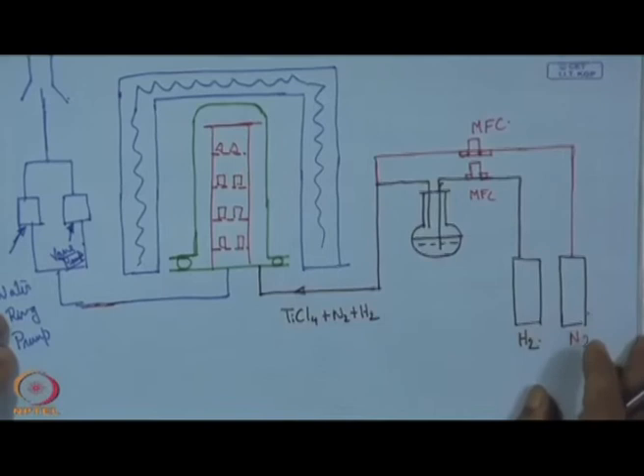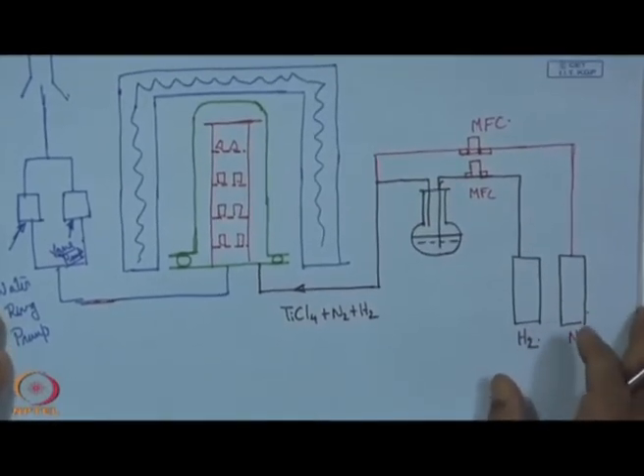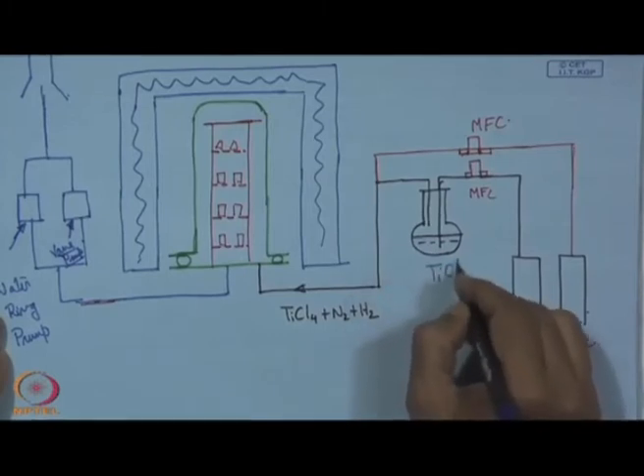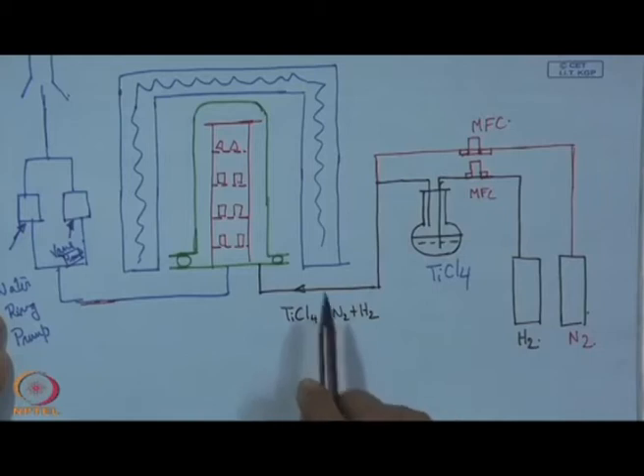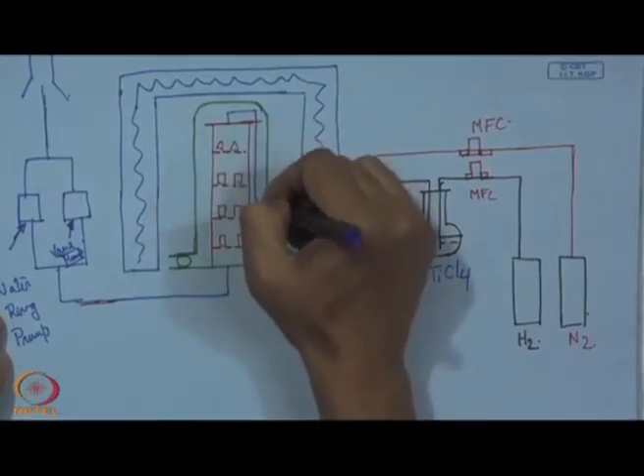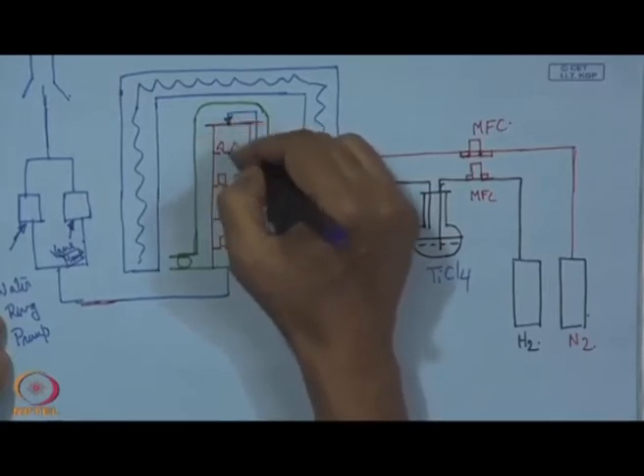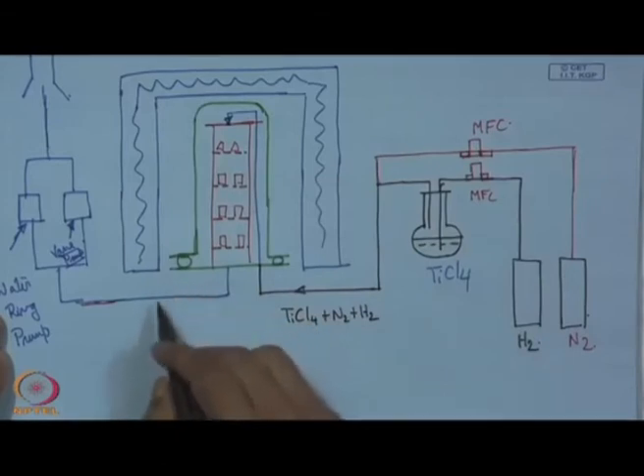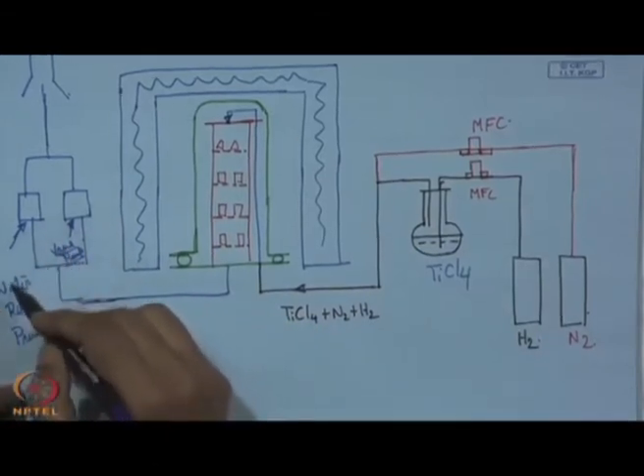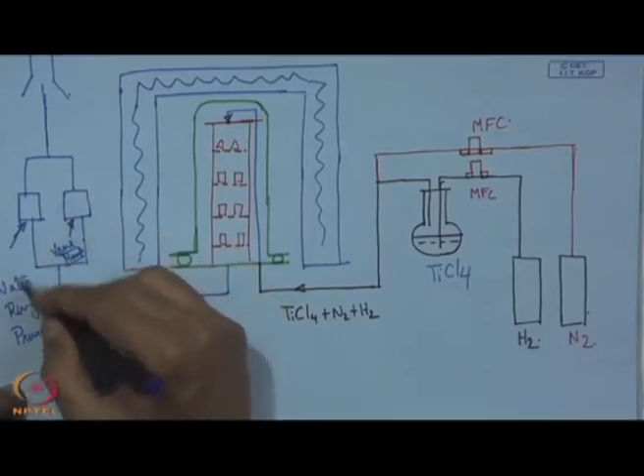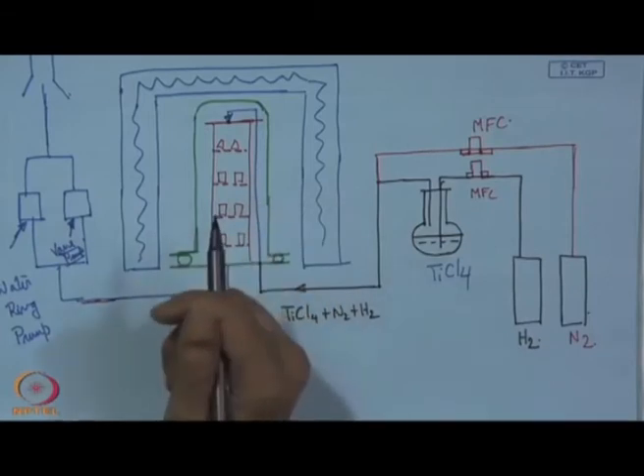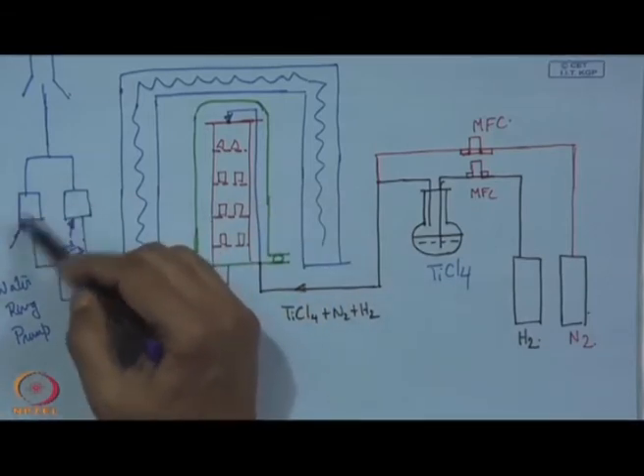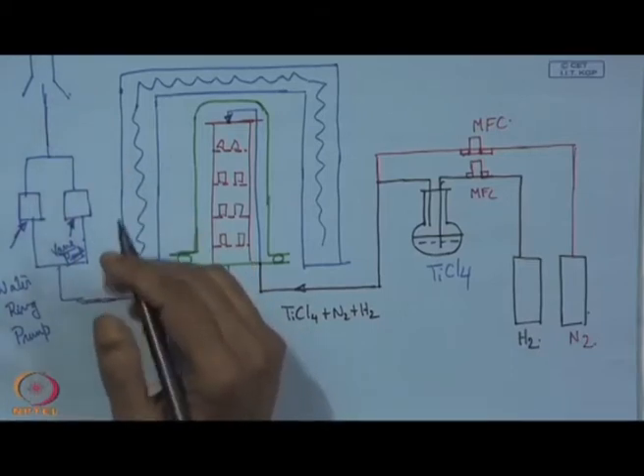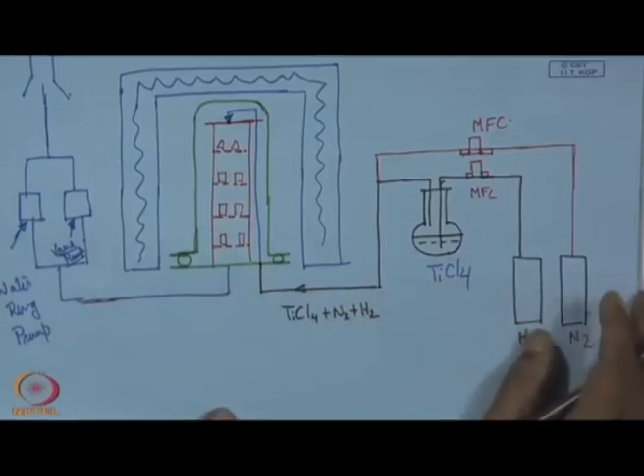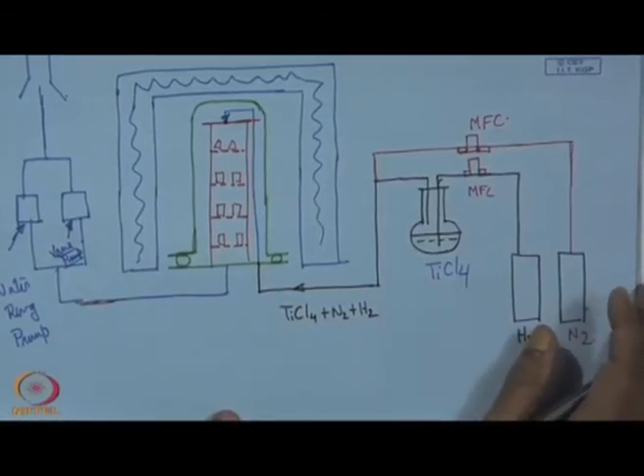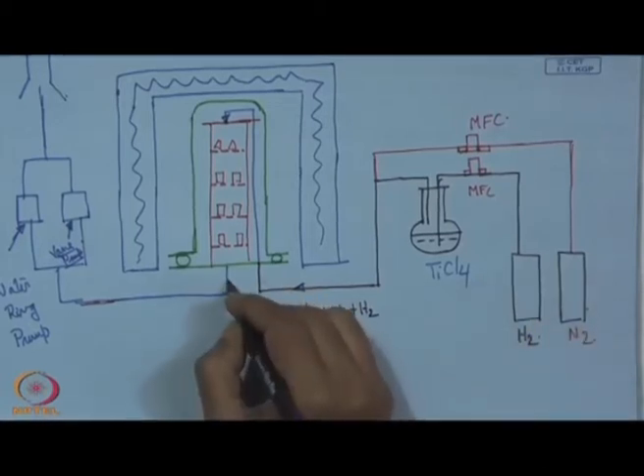So, these are basically the CVD setup what we can see here, and this is TiCl4. So, these are admitted and this will go over this surface and it will be showered, and as the outcome we have HCl. So, during the CVD operation this vane pump does not work, it is actually the water ring pump where this HCl is neutralized and any residual gas will escape through this ventilation. So, this water ring pump, or the liquid ring pump, contains sodium hydroxide which is used for neutralizing this HCl.